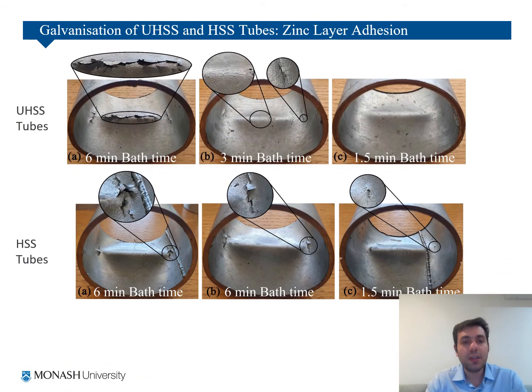As you can see, by decreasing the bath time, the coating is working better after impact. For example, for UHSS tubes, you can see that the coating is very brittle for a 6-minute bath time. But if we decrease the bath time, it is working better, and the coating is more robust. And this is because the coating thickness is much higher for 6-minute dipping.